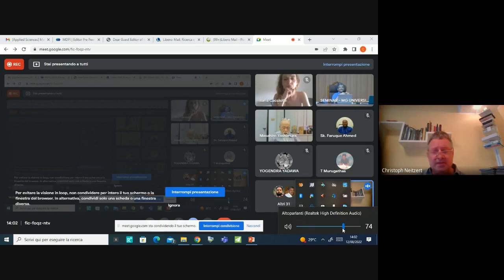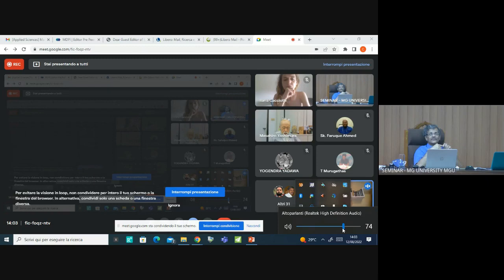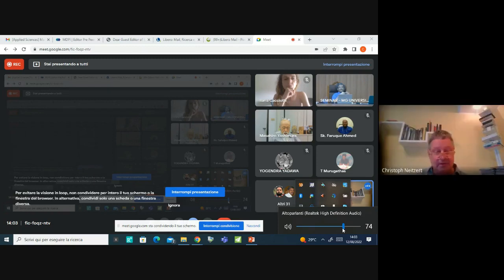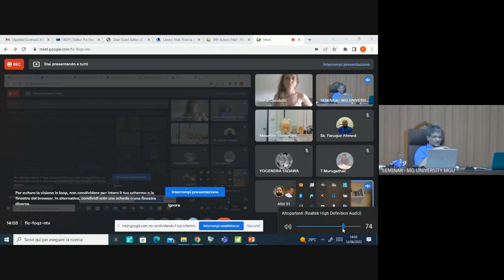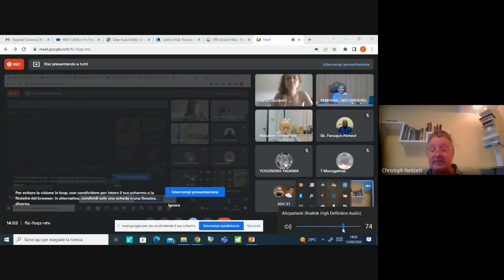It's affected, but you could use this as a moisture sensor, for example, for airplanes. You could use it for de-icing, but you can also use it for revealing the moisture content. With epoxy, it works up to 200 degrees. It's a perfect heater, a very good heater with self temperature sensing and self humidity sensing. But if you heat it, then it's zero humidity. Then it's an optimal temperature sensor.